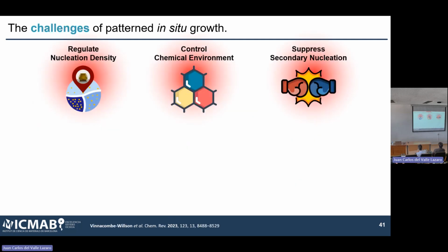So the challenges of in situ growth, the reason why it hasn't been studied that much, are basically these three main challenges if you look at all the literature. First, we cannot regulate the nucleation density, so we cannot tell our system, you need to nucleate a particle here, here, here. They just nucleate everywhere. Second, it's very hard to control the chemical environment, because the chemical environment includes the substrate. Every substrate is different, and it's not as homogeneous as a solution. If you have a substrate, it's not identical here, here, here, here, unless you're really careful in how you fabricate the sample. And third, you have to suppress secondary nucleation, as I just mentioned.